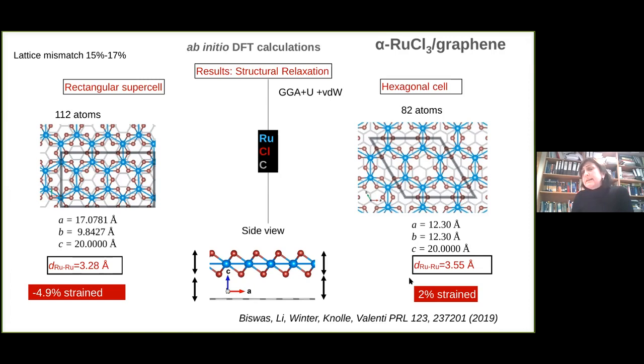And in this cell, ruthenium trichloride basically expands. So what I get is that the distance between ruthenium atoms gets larger. This is going to be important because I'm going to get rid of some interactions that are detrimental for a pure Kitaev-type description. And this is basically the side view of this heterostructure.